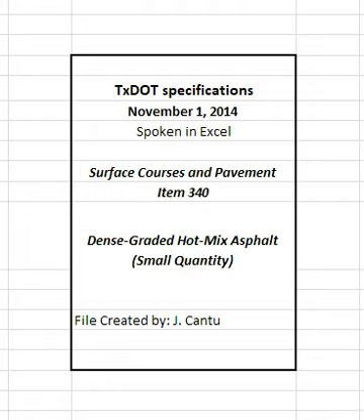approved. Test the stockpile if 10% or more of the stockpile is retained on the number 4 sieve, and verify that it meets the requirements in Table 1 for crushed face count, TEX 460A, and flat and elongated particles, TEX 280F.